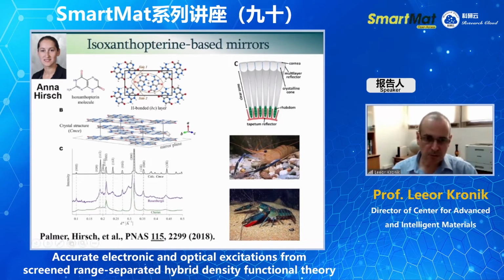So we played around with various structures on the computer based on essentially crystallographic information and a simple idea that says that we want to maximize hydrogen bonding. So we did that together with a wonderful crystallographer, Leslie Lazarowicz. And finally, we were able to come up with this planar structure.